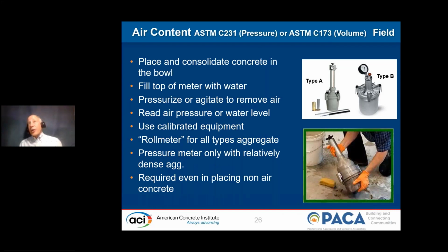In my opinion, the second most important test is the air content, and the one that takes the most time in the field to do. You see here in the picture the 2 types of meters: the pressure meters on the upper right-hand picture, both type A and B, of which type B is the most common one anymore. You don't see type A hardly at all. And then below that is the volumetric meter, most often known as the roller meter, as you can see this gentleman rolling the roller meter here.